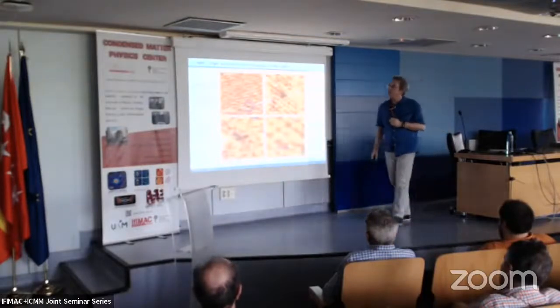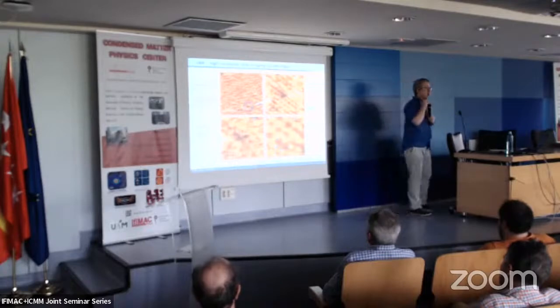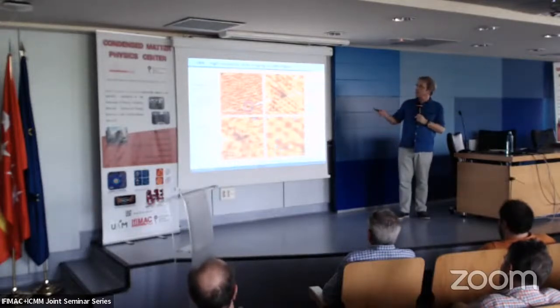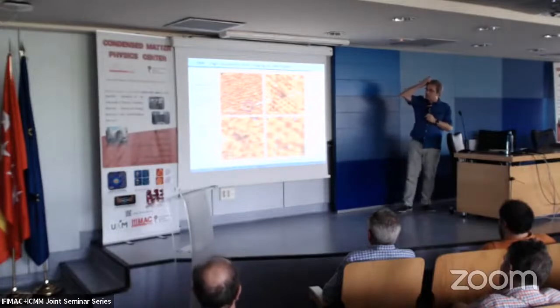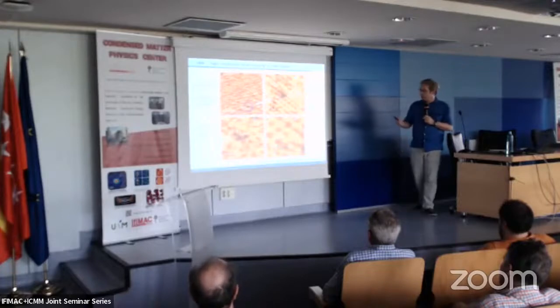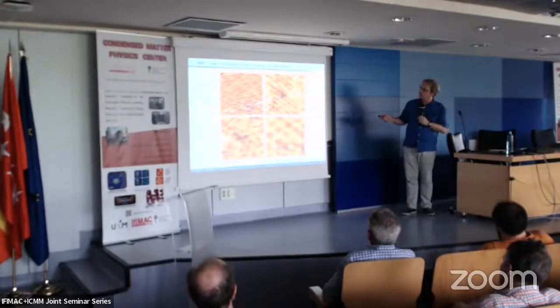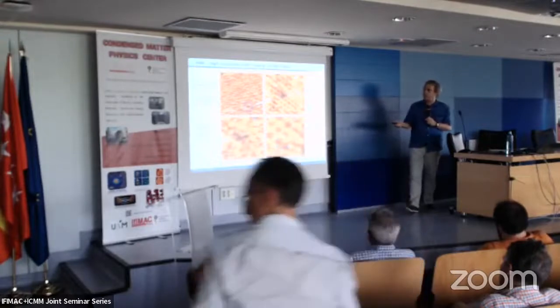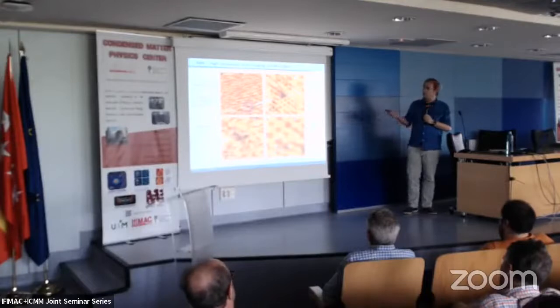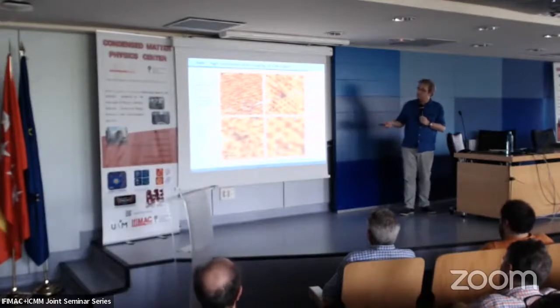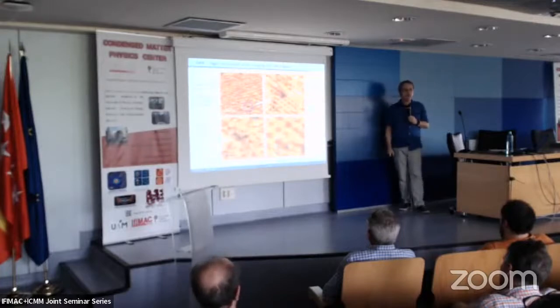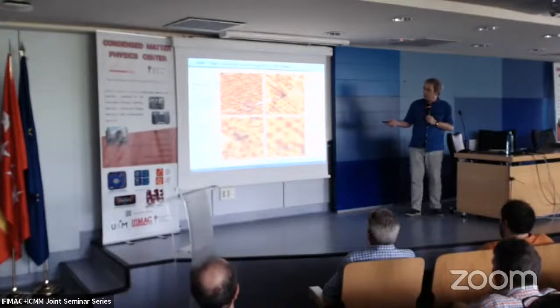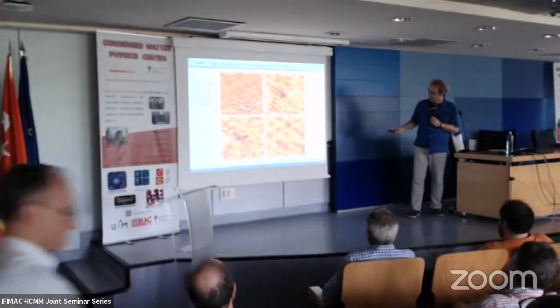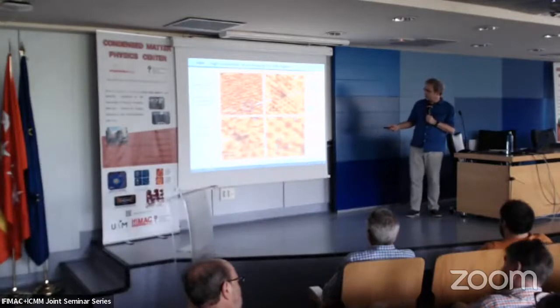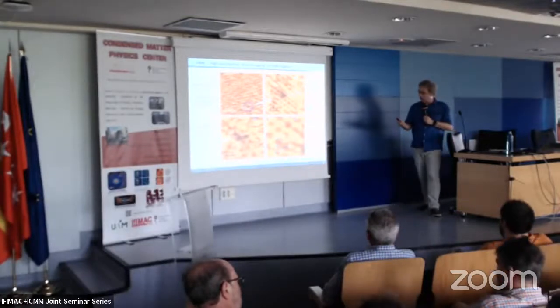Now this work on hexagonal boron nitride was part of a bigger investigation where other groups were also involved. And here we see the high resolution images made by Pablo Ares of the kind of defects present in this hexagonal boron nitride. So the idea was to try to identify these defects and possibly connect them to some kind of emission. This is three vacancies, so the 3 borons and 1 nitrogen missing, and this one is the one which we used in the calculation on the previous slide.